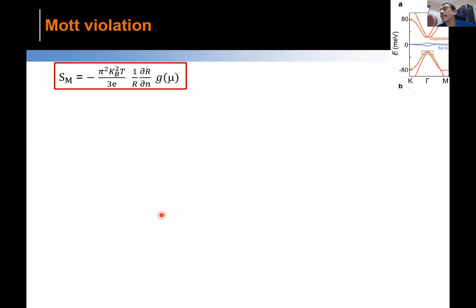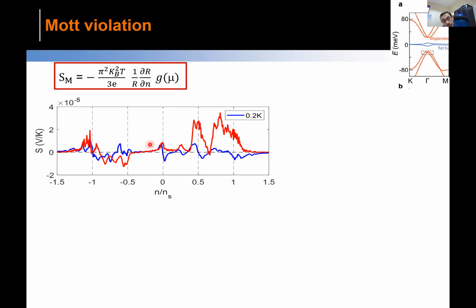Now you try to ask, what is my expectation? As I was telling you about the Mott formula, it goes as the derivative of resistance. And if you remember, resistance has a peak at the neutral point, your Dirac point, and at integer filling you have this resistance peak. If I take a derivative of that, it will give me a crossing. In fact, at the integer filling, I should see a zero thermopower.